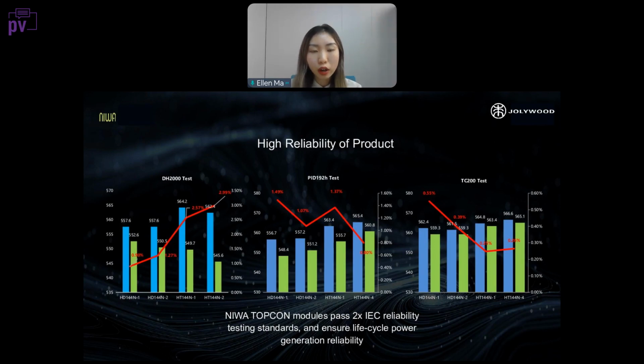And then, we have talked a lot about the advantages of our products. So how will they actually operate under outdoor environments? Here we have come up with 3 tests. The first test is the DH2000 test, which stands for the damp heat test. We can see the numbers here. After the damp heat test, the degradation rate is less than 3%. We also did the PID test, and after the PID test, the degradation rate is still less than 1.5%.